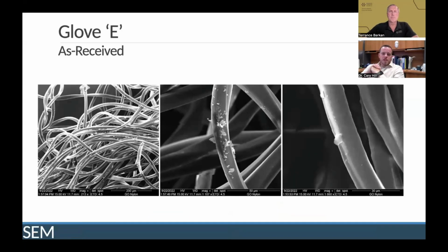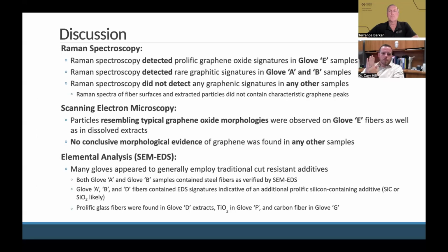And then we see here in the as-received glove morphological evidence of the graphene oxide. No compositional identification in situ here, but you can see the additive is embedded within the fibers and on the surface of the fibers, this flake-like material. So it's circumstantial evidence pointing towards the same conclusion. I believe we have more on the next slide. Oh no, I guess I cut out the slides. There are others where we zoomed in. You can see more of the flakes in higher detail.